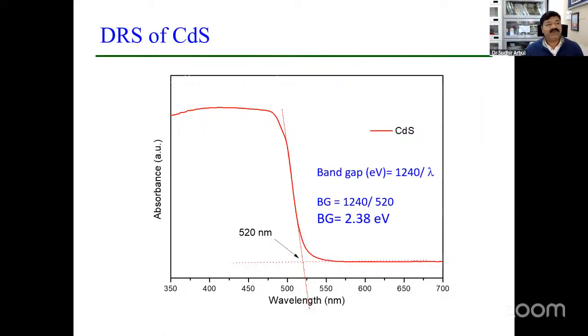Okay, now we have taken the diffuse reflectance spectrum of cadmium sulfide. If you take it dispersed in a liquid and record the spectra, it will not come out correctly. It will give you wrong information. But if you can get the DRS spectra of cadmium sulfide, you will get this kind of nice picture. Roughly, absorbance versus wavelength: if you put the tangent on both axes, it meets at 520, and this is the band gap formula, 1240 divided by wavelength in nanometers.